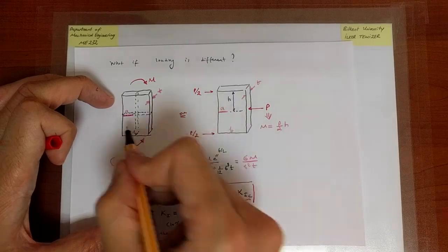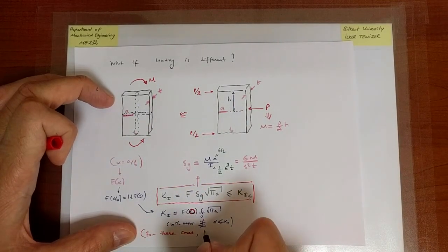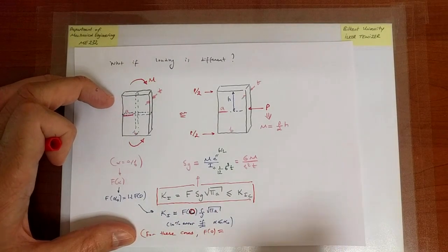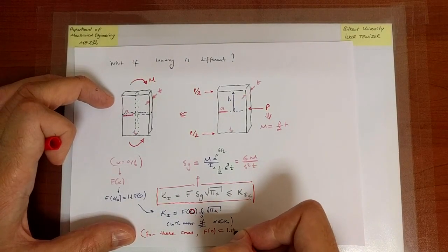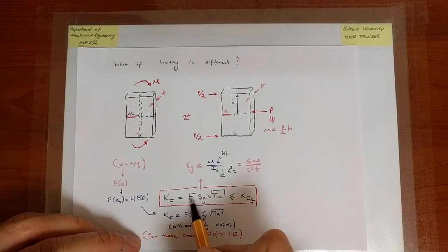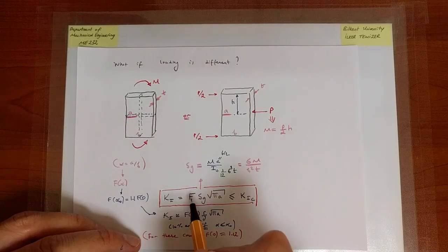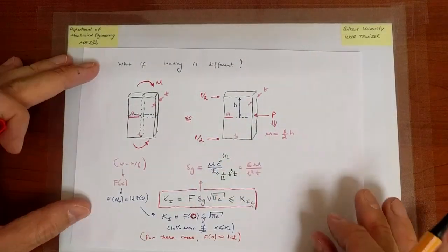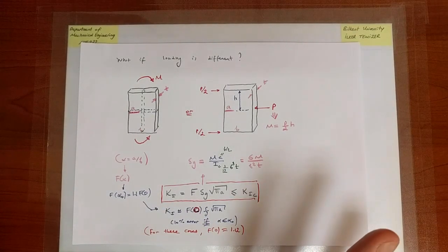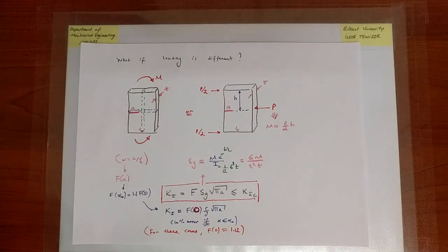so for these cases that I am considering, F of 0 is, unlike our prototypical case and like the two other cases we have considered in the previous slide, equal to 1.12. It's not 1. So the limiting case puts not 1, but 1.12, because this geometry is special, and that's the correct limiting value of F. Okay? So now we've said a lot, we've written a lot. Now I think it's a good time to go ahead and apply these expressions and ideas to an example.